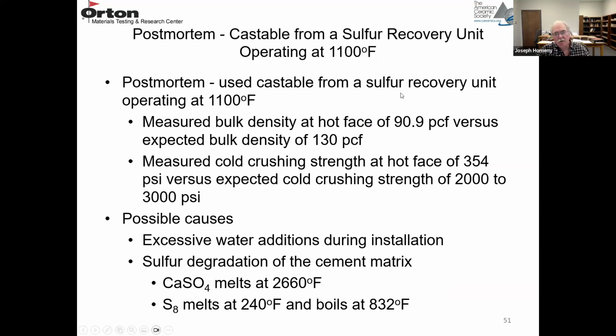So this was a castable from a sulfur recovery unit operating at a pretty low temperature, 1100 F. So you can do other things in a post-mortem study. In this case, density and strength was measured. So the density at the hot face was about 91 pounds per cubic foot. The expected density of this particular castable, we were told what type it was, should have been about 130 pounds per cubic foot. So the hot face is lighter than expected, and the cold crushing strength was measured at about 350 psi on the hot face. This castable should have been 2,000 to 3,000 psi after curing at this temperature, about 1100 F. So it's very weak, it's low density.